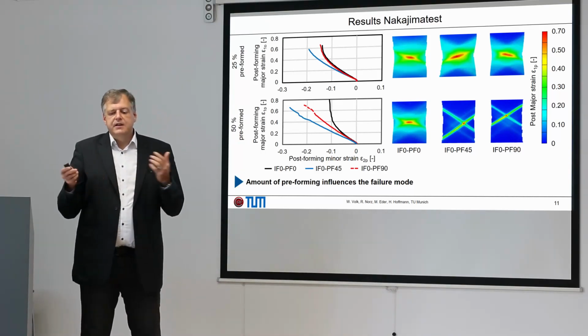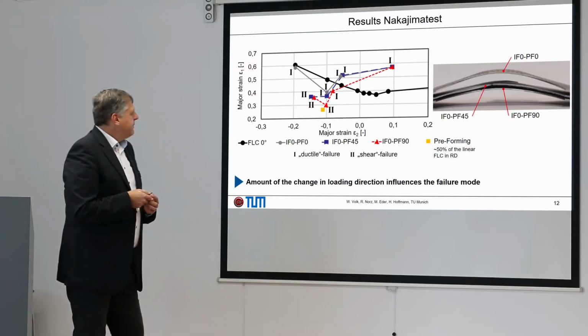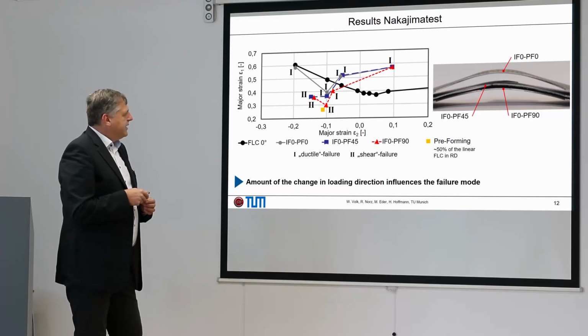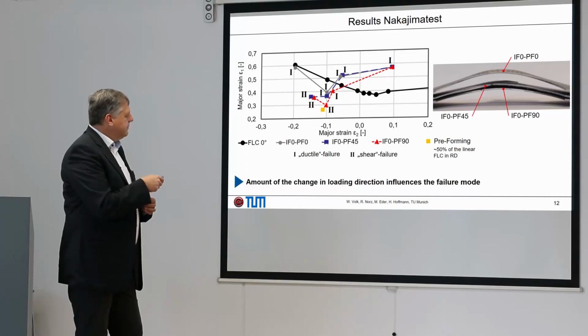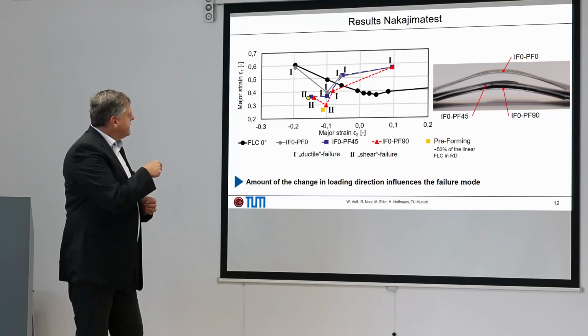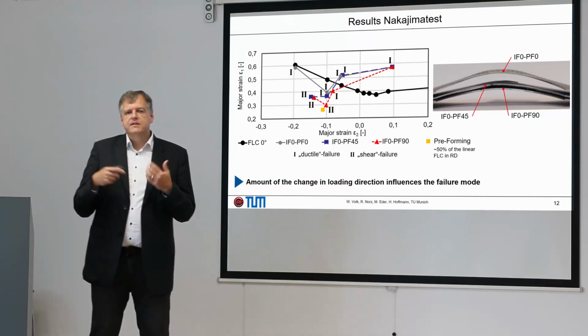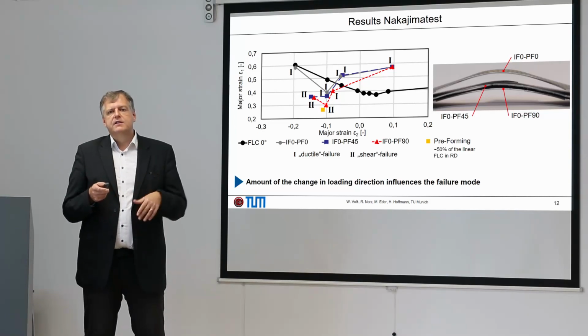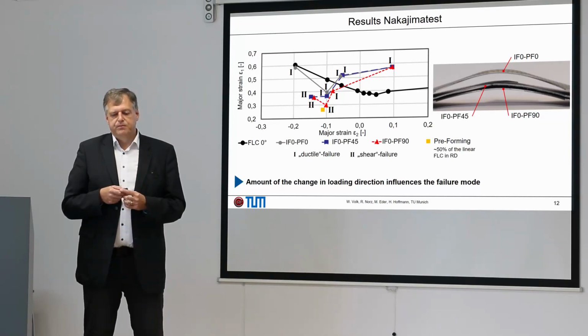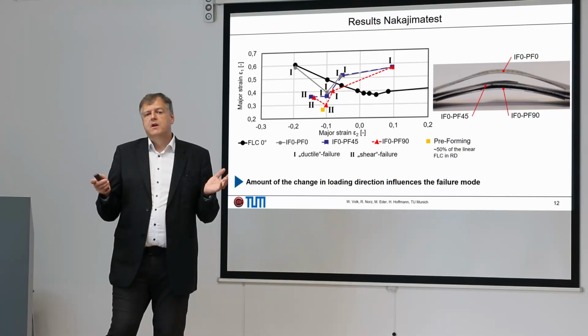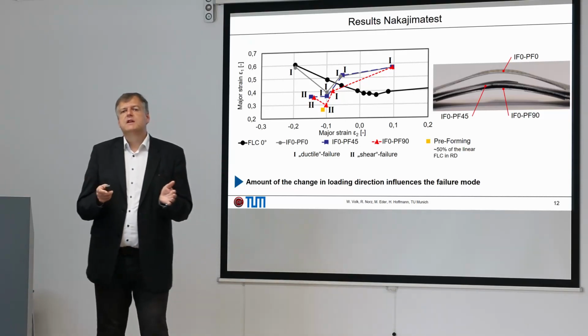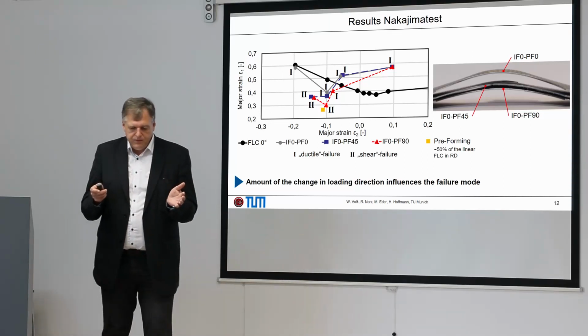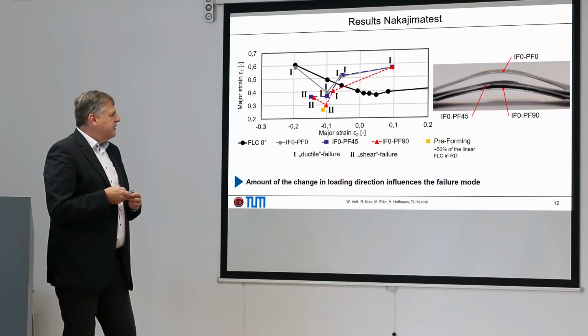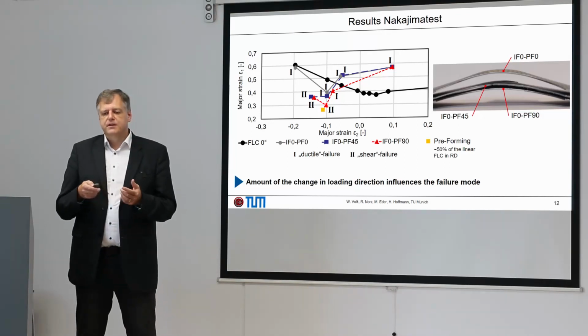And now let's see in our total map of experiments where we have this conventional failure mode with our plane strain failure and where we have this ductile shear failure. And it's obvious that all the points where we have this significant reduced formability, this shear failure occurs. But now the question, why? What's the reason why we have this different failure modes? And therefore, it's helpful to have a microscopic view in the specimen.